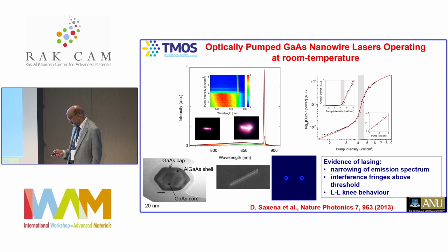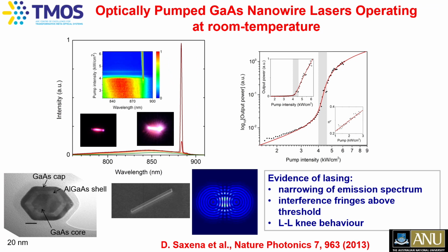Again, to cut the long story short, with the help of Dr. Jenny Jiang, who is now at Cambridge University, she has grown these so-called gallium arsenide, aluminum gallium arsenide core-shell structures. And then we transfer them onto a glass slide and excite them with a laser pulse and look at the light emission. You can see that below threshold, you see a broad light emission like an LED. Above threshold, you see a narrow light emission like a laser, with beautiful interference fringes.